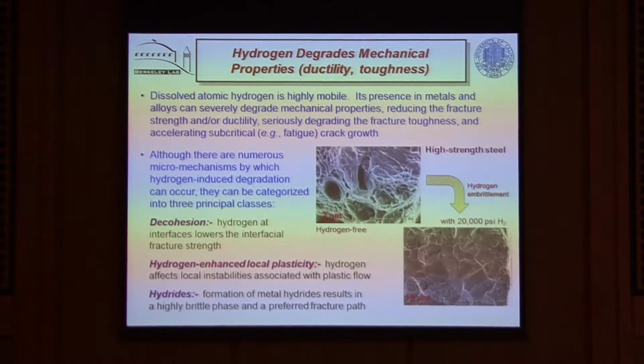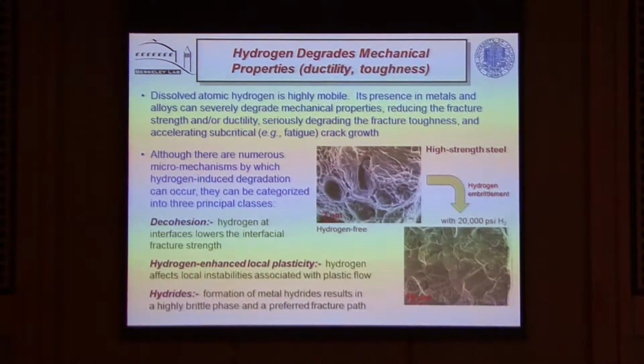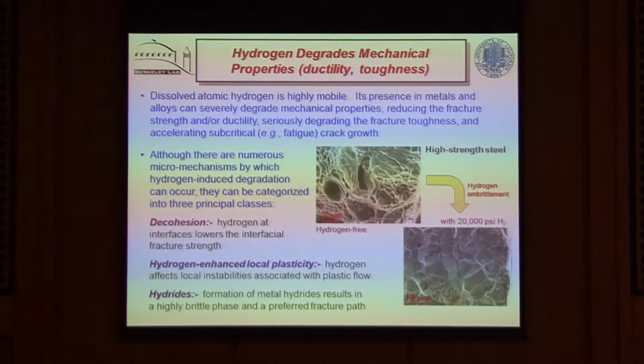Well, many of you, of course, know this very well, but hydrogen is a particularly onerous entity. It is extremely mobile, of course, being small, in its diffusion, and its presence can severely degrade the properties of all metallic materials. This is paramount in many different forms. Obviously, it reduces the fracture strength. The material becomes, in some respects, more brittle. It can degrade the ductility of the material, how much strain it can tolerate before it fails. It can severely affect the fracture toughness, which is its fracture resistance. Typically, a high-strength steel in the presence of hydrogen has about 1/4 of the toughness that it might have in the absence of hydrogen.